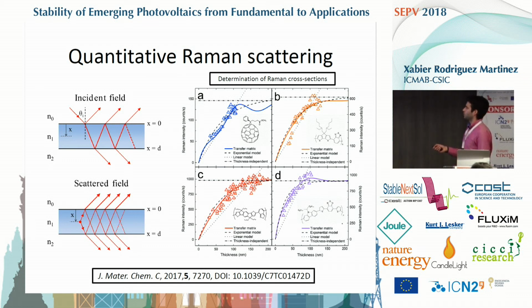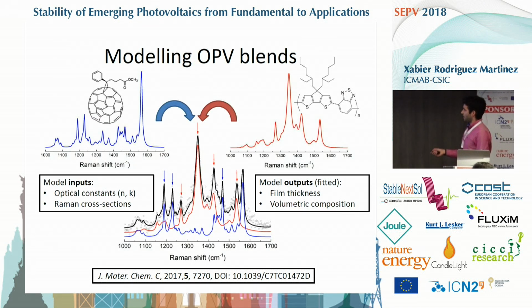We basically applied transfer matrix modeling to a typical Raman experiment, in which we are taking into account all the interferences in the whole stack of your device or the supported film. And basically, this allowed us to extract the cross sections of the materials. We applied exactly the same approximation to OPV blends. This means that when we blend both materials in a film, we basically have to take into account the optical constants of the film and the Raman cross sections of the materials blended, and from here we are able to obtain the film thickness and the composition of the films.